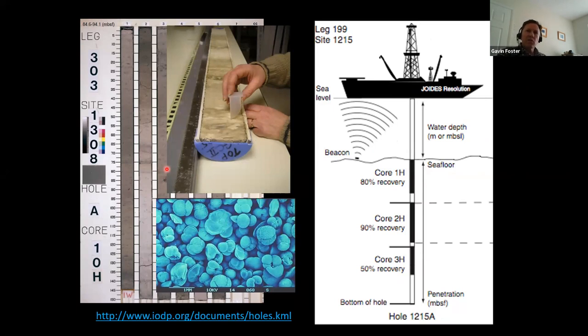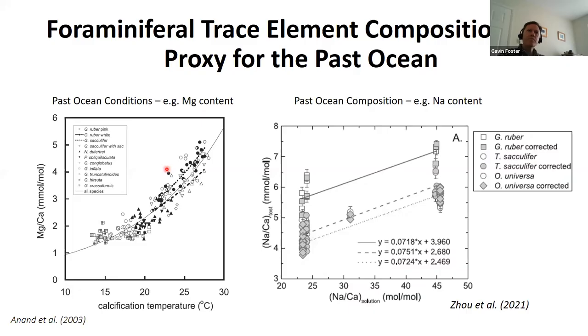So we have this continuous climate record over all that time based on the chemical composition of the calcium carbonate, the calcite shells of these foraminifera. So what we can use the forams for is actually the multitude of traces of past environment. We can look at a number of chemicals that are in the calcite shells to reconstruct past ocean conditions.